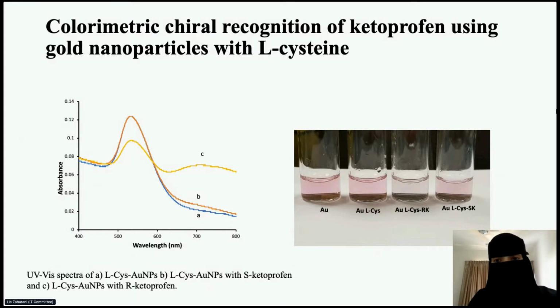As you can see in the UV-Vis spectra, A is the L-Cysteine capped gold nanoparticle. This peak corresponds to the gold nanoparticle at 536. It's a nice peak, so the gold is spherical. There is a spherical gold nanoparticle. When we introduce S-Ketoprofen, B is L-Cysteine capped gold nanoparticle with S-Ketoprofen. No change in the color, as well as the absorption peak, indicates no selective response toward S-Ketoprofen.